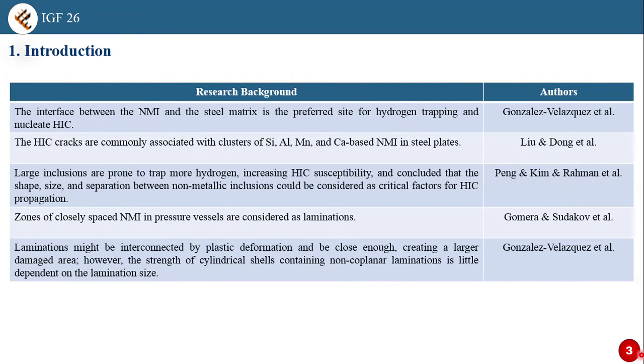The presence of non-metallic inclusions in pressure vessels made of low carbon steel exposed to sour environments is one of the main factors that increase the susceptibility to hydrogen-induced cracking, or HIC. The zones of non-metallic inclusions are considered as a lamination, and fitness for service assessment is done by a methodology similar to that of lamination. This table shows the research background of authors who worked on the effect of non-metallic inclusions on the remaining life of pressure vessels.